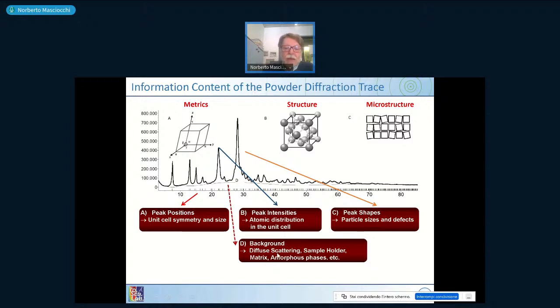Again, I show you that here there is a trace below the major peaks. This is the background. The background can depend on diffuse scattering. We will come back later to what diffuse scattering is. It can be given by the sample holder, by the matrix where the material is encoded, by amorphous phases, or simply by misalignment of the instrument, or some ambiguous intensity which comes from other portions of the diffractometer and not directly from the sample.